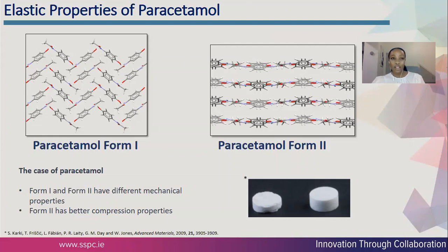And this is shown by the image here on the bottom right, where the first tablet is that of form 1. And as you can see, form 1 struggles to form a tablet. The second tablet is that of a stable multi-component crystal of form 2, and it is able to form a perfect tablet. The layered structure of form 2, though, only provides a tentative explanation for the improved compaction properties that we see. And to further explore the relationship between crystal packing and mechanical behavior, computational methods can be adopted.